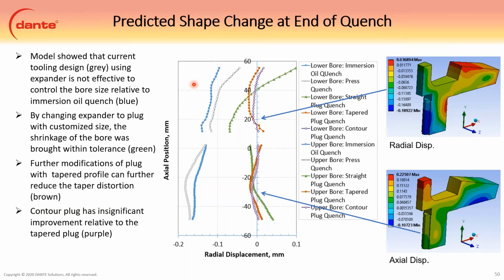So what happened here is that this is the top portion of the bore, so it's this portion, and this is the spline down here. So the blue line is what would happen without constraint. So if I just dumped this in an oil tank, this is the prediction. The gray line was the process that the customer was currently using. And you can see, especially on the spline, it actually made the distortion worse. So their thought was, by constricting it, I'm going to make the distortion better, but in reality, they were making it worse. So what we did was we came in and said, okay, forget the expander, which essentially puts a load on the bore. And we said, use a plug, which is a solid cylinder that goes inside of the bore. That's the green line.